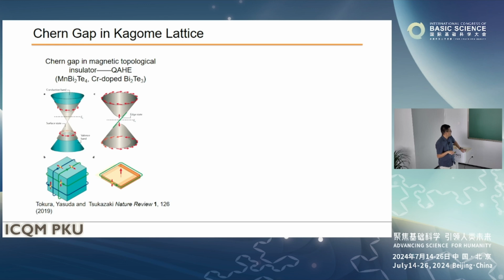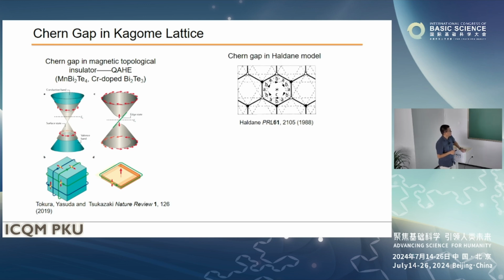So the simplest example is if you have a topological insulator, you have a surface state that is a Dirac cone, and when you break the time reversal symmetry, that will further open a gap. That gap is a Chern gap, and you have a protected edge state. And if your Fermi level is around here, you measure the Hall resistance, you find a quantum anomalous Hall effect. Actually, this effect was predicted by Haldane, in a Nobel Prize paper in 1988. So you have a honeycomb lattice with a staggered magnetic interaction. You see a Chern gap in the Haldane model.